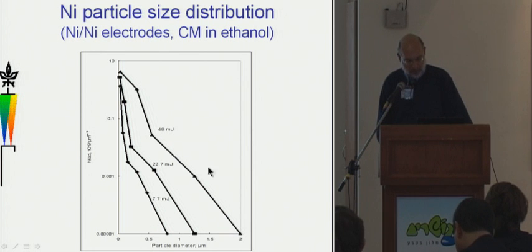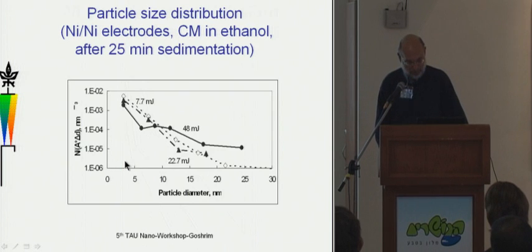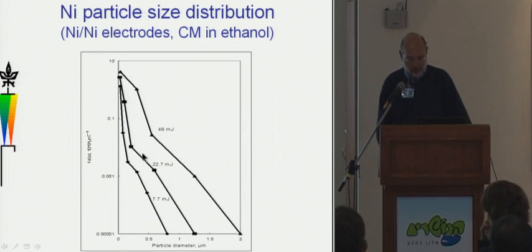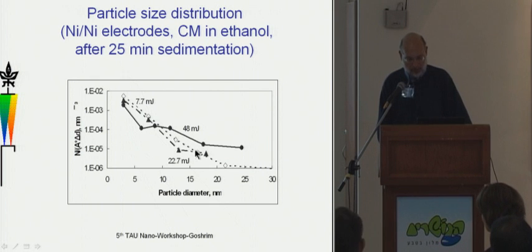What's clear here is that there are many, many more small particles than large particles, and that the distribution function very much depends upon the pulse energy. As we go down in pulse energy, the fraction of smaller particles increases. No big surprise, but it's good to know. This is from all of the particles that we collected after evaporation. You get much more smaller particles if you allow the big particles to settle out, the micron-sized particles, and then work with what's left in suspension. Well, that's also good news, because sedimentation is a cheap process to employ in a factory.